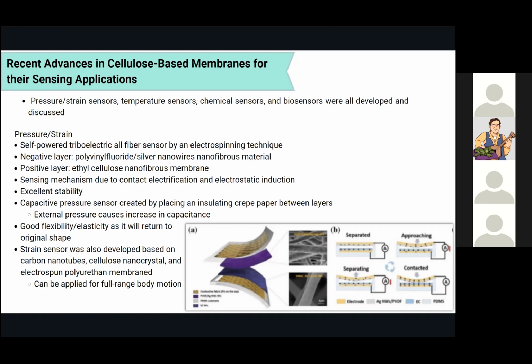So by placing a piece of an insulated crepe paper between the two layers, you can actually take this and form a capacitive pressure sensor. But when an external pressure is acted, the capacitance increases with the decrease of distance between the conductive membranes. When it is removed, the shape of the sensor will actually return to its original shape due to its stiffness and elasticity. And then a strain sensor was also designed based on carbon nanotubes, cellulose nanocrystal, and electrospun polyurethane membranes through a one-step filtration method.